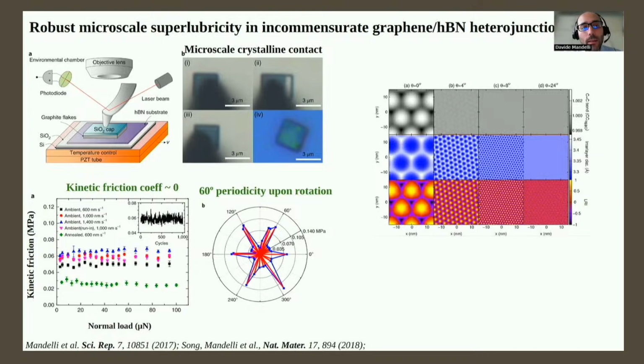In the case of graphite or graphene over hBN, these mass density waves correspond mainly to out-of-plane distortions, and these are shown here in blue and white in the central row, which are maximized for the aligned case, hence the maximum of friction at a multiple of 60 degrees. And then as we rotate, they die off until for very large angles, there are no out-of-plane distortions anymore, which is consistent with the observation of very low friction at high misalignment angles.